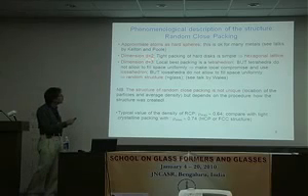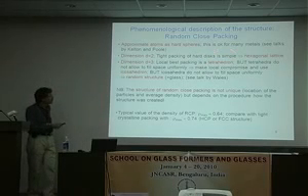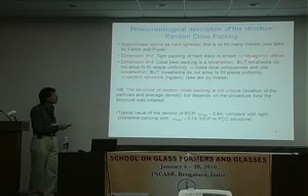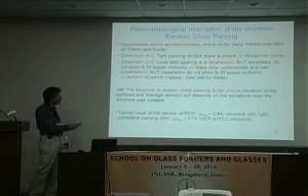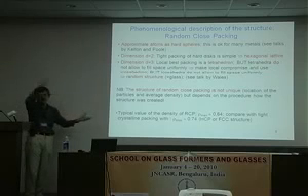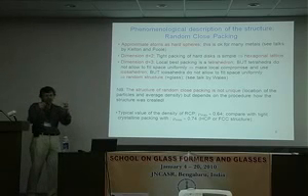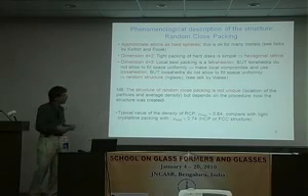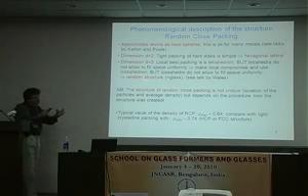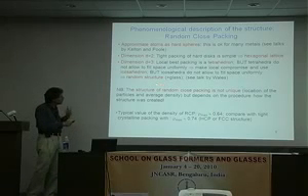If you are in 2 dimensions, the spheres become disks. If you want to tightly pack disks, what you get immediately is a hexagonal lattice. In dimension 3, the motif that is best packed locally is the tetrahedron. So you have 4 particles, but with tetrahedra you cannot fill the space uniformly. And so what you do is make a local compromise. You cheat a little bit. You take a few of these tetrahedra together and you form an icosahedron, which is a very good local packing. But again, with icosahedra you cannot fill the space uniformly. And so if you take the structure and you try to pack them as efficiently as possible, you get a random structure. That is to say, a glass.